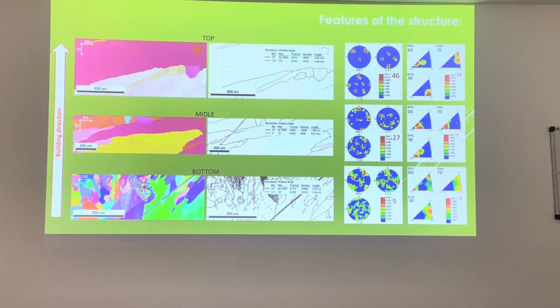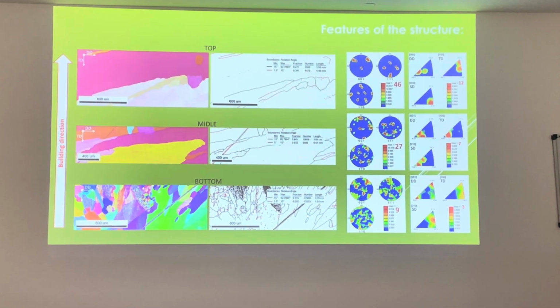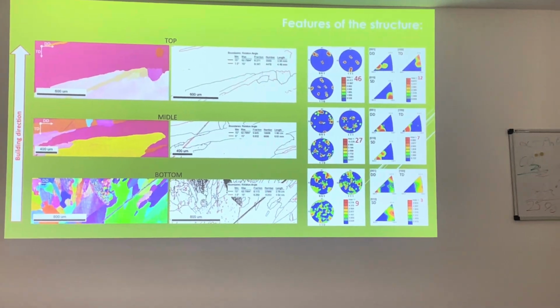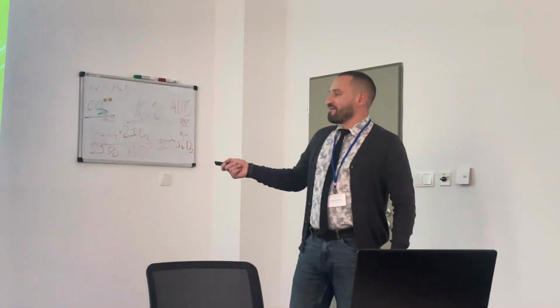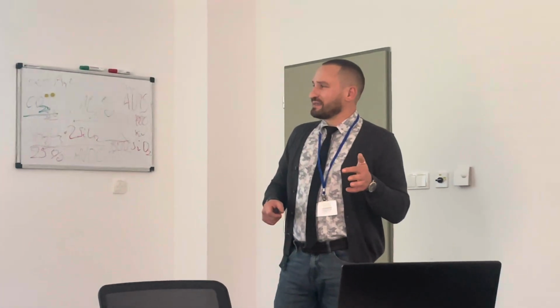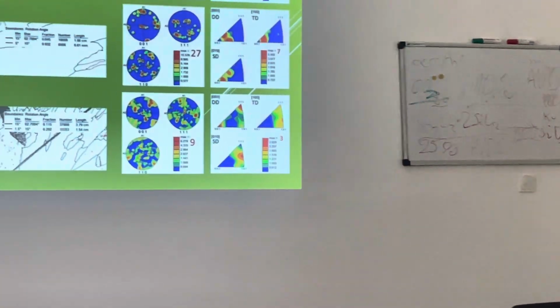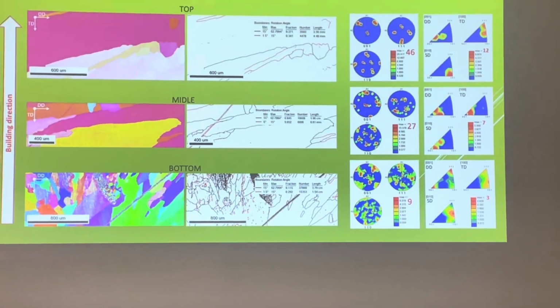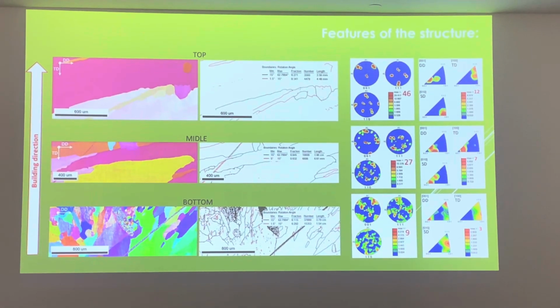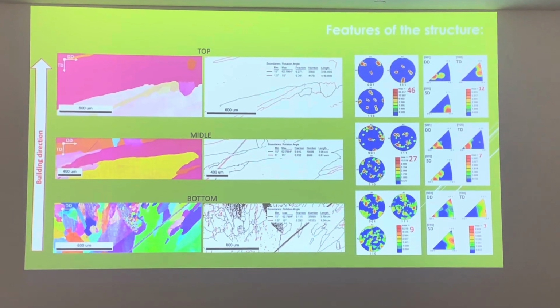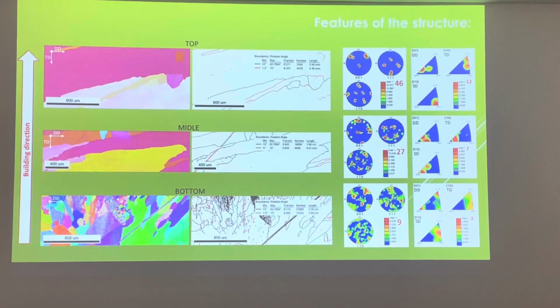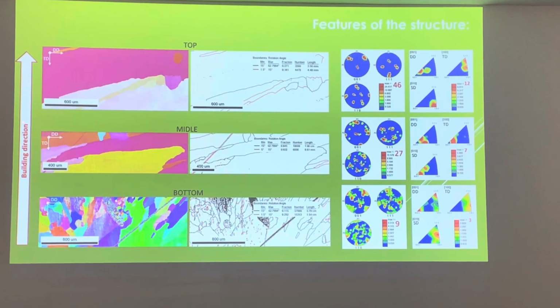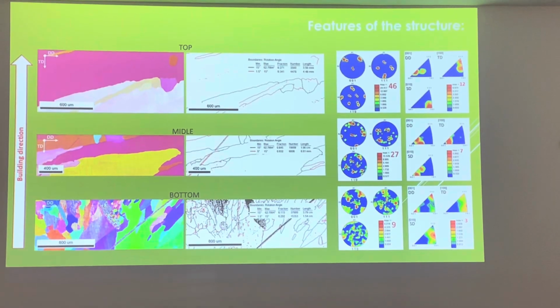Next step, also for characterization, we have made electron backscattering diffraction, also from bottom to top. We have observed dependencies that at the bottom part of the billet, the grains are finer than at the middle and at the top. This is connected with the heat flow, because the first layers of the deposition have a much higher cooling rate on a cold substrate, and after several multi-layer depositions, the cooling conditions become different, and the cooling speed becomes lower, and we have obtained more and more big grains from bottom to top.